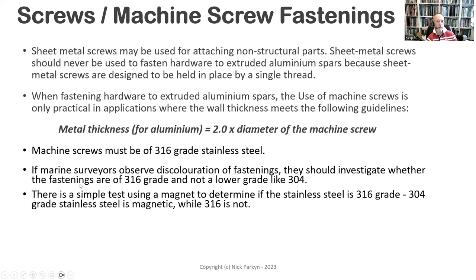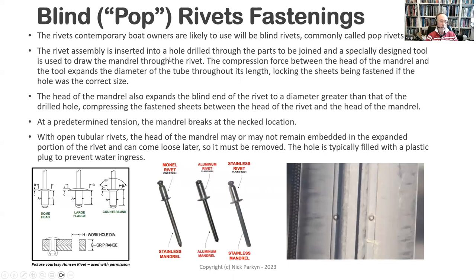Machine screws must be 316 grade stainless, and typically discoloration of the fastenings is often an indicator that the fastenings are actually of lower grade, 304 stainless or similar. And as we all know, there's a simple test: 304 stainless is slightly magnetic, whereas 316 is not. In terms of pop rivets, as we said, there are a lot of fittings attached to aluminium spars using pop rivets.